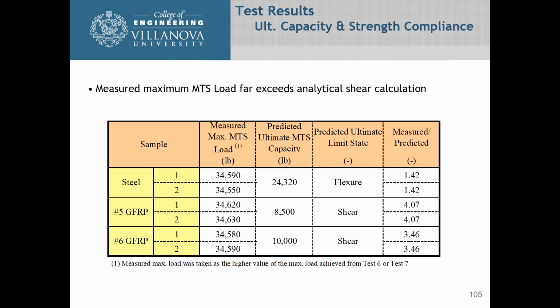So by doing this, you can see that the actual load on the MTS far exceeds the shear capacity. For the steel, our predicted ultimate limit state was flexure, and for the two GFRP bars, it was shear. So we predicted, you can see what we predicted the capacity was versus what we actually measured, and you got a ratio. For the steel, we're about 1.5 times more than we predicted. But you can see for the GFRP bars, the failure was supposed to be in shear, and we got 4 times the capacity for the number 5 and 3.5 times the capacity for the number 6.